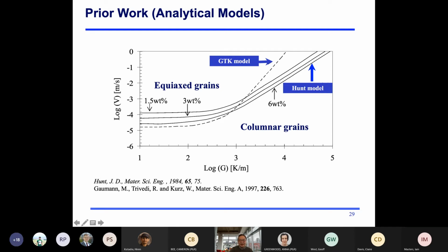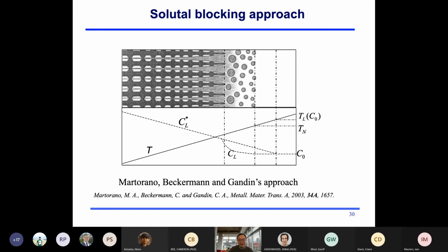If your processing condition is in this kind of area, you grow equiaxed grains, and if you are at this kind of level, then essentially you have a high thermal gradient and low growing velocity, and you form these columnar grains. So this is the earlier kind of study, using an analytical way to analyze them. And today I will show you using a computer simulation method to simulate this transition from columnar to equiaxed.